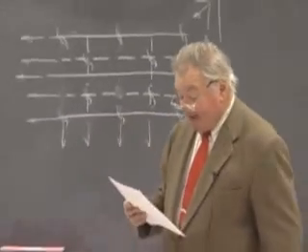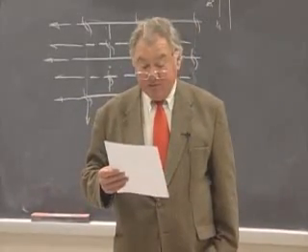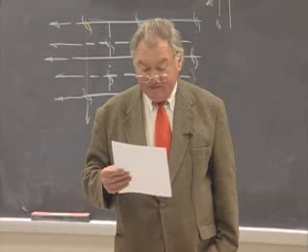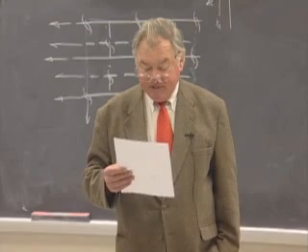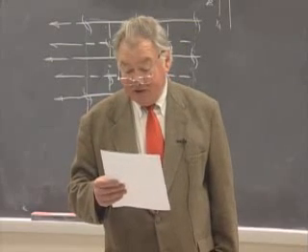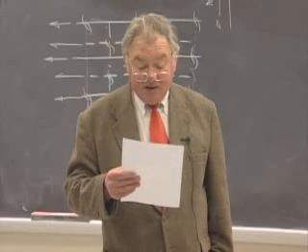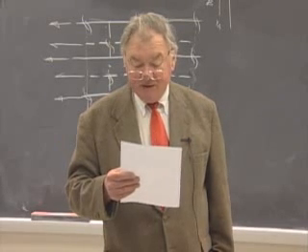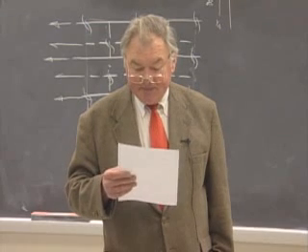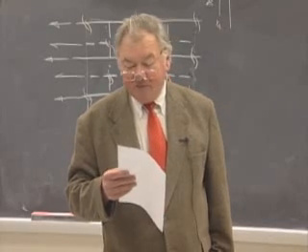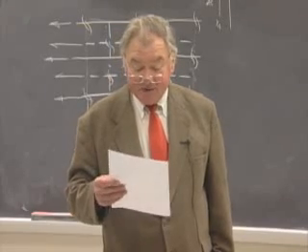So first of all, some indication of what's on the lower part of the page. This is exactly analogous to what you've seen and presumably are familiar with for the two-dimensional plane groups. There are many possible origins that could be selected for the 0, 0, 0 position relative to which the atomic locations are expressed. So the first thing just below the picture of the arrangement of atoms and the depiction of the arrangement of symmetry elements is a statement of where the origin is. So it says origin at the center, inversion center, 2 over m. And if you look at the arrangement of symmetry elements, there is nothing but the representation for screw axes normal to the page, but there is off on the right-hand side a solid chevron, and that is the indication for a mirror plane.